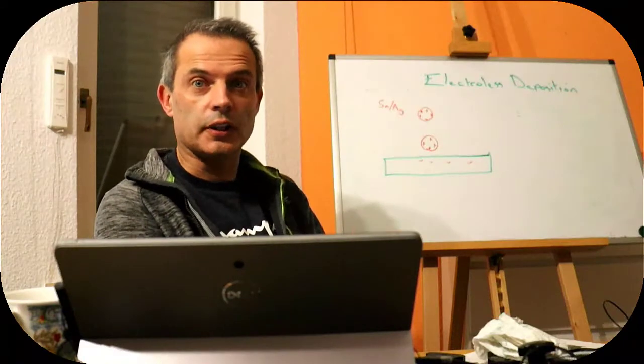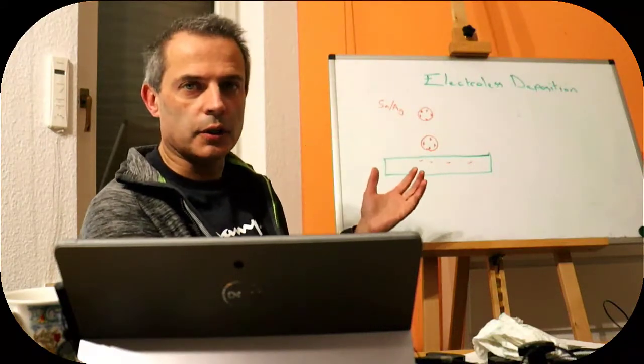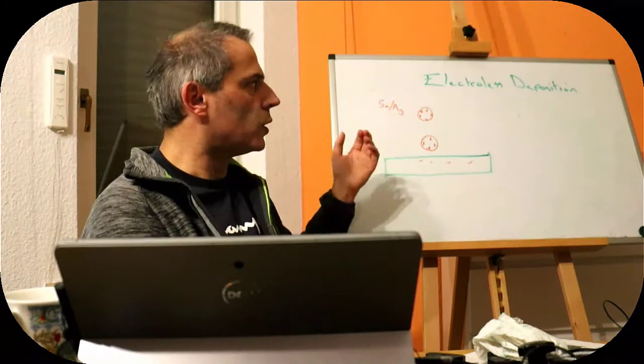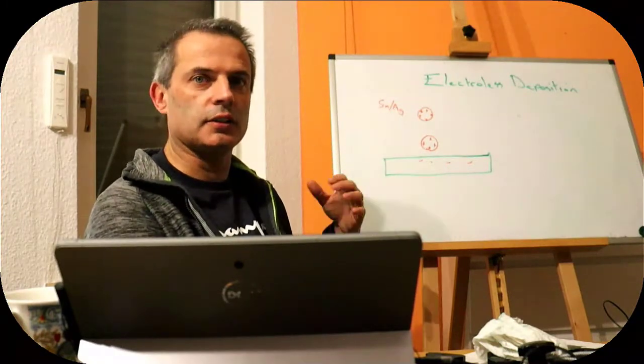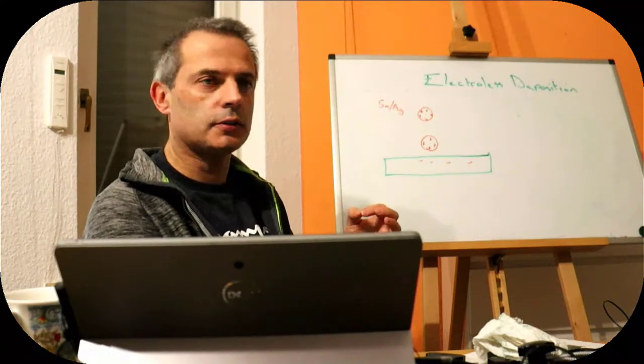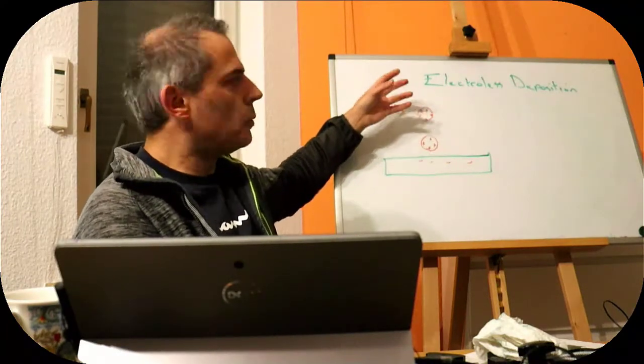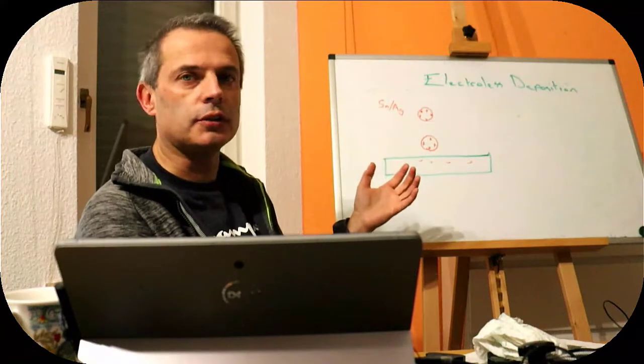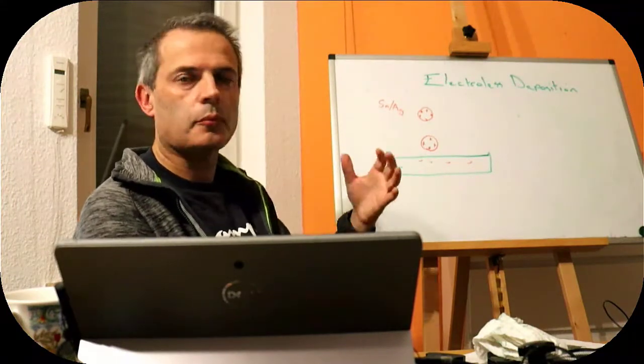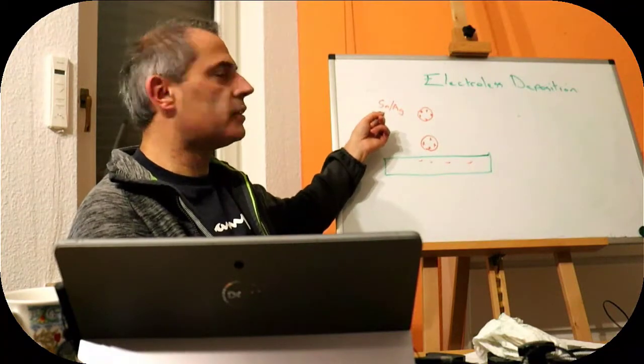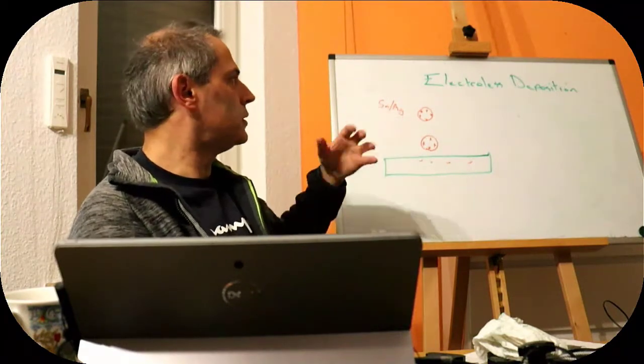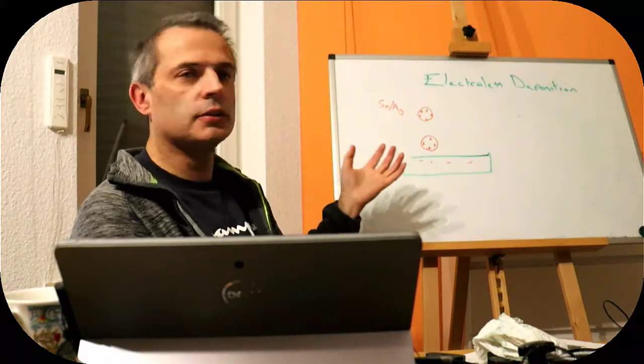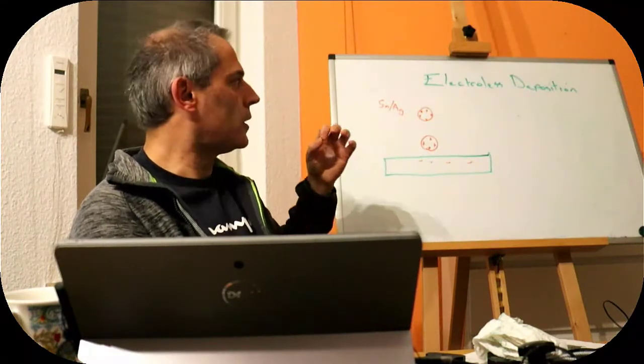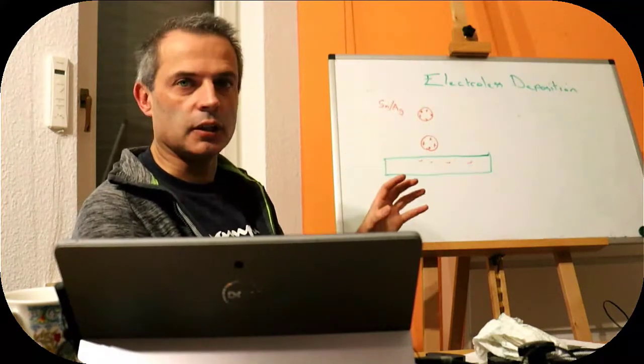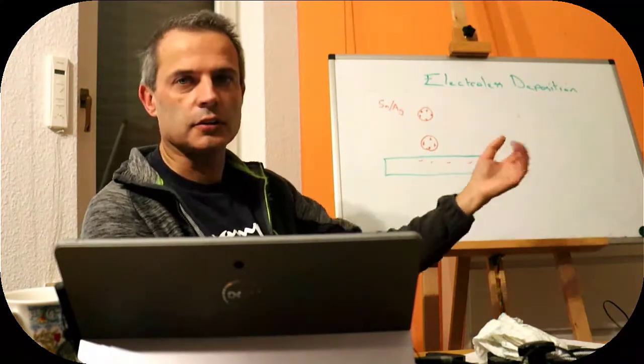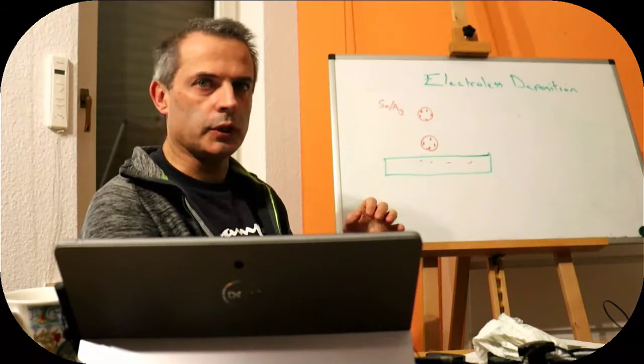So a quick excursion into colloid chemistry. If we have a tin silver particle, which might be what we're going to use, it's one of the proposed ways of having a cheaper catalyst that isn't palladium for making copper surfaces. We make it positive by either having a positively charged surfactant at the surface, or simpler, we have an excess of metal ions. So we have our tin silver particles in a silver solution. The silver ions will interact with the surface and make it slightly positive. Our surface could be glass, and glass is naturally negative in most pHs.